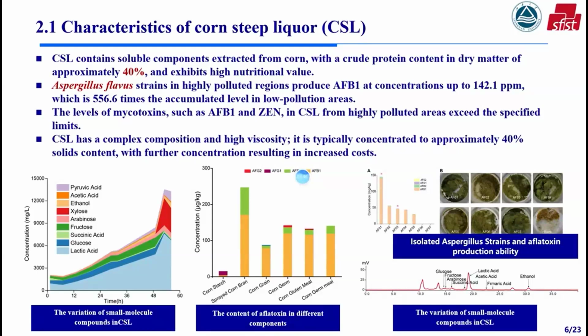susceptible to aflatoxin contamination. Strains isolated from different regions have different toxin-producing capabilities, and those from high contamination areas have significantly higher aflatoxin-producing ability than those from low contamination areas. Strains from high contamination areas can accumulate up to 142.1 ppm of toxins, which is more than 500 times that of low contamination areas. Besides aflatoxins, ZEN is also frequently detected in CSL. CSL is usually concentrated to 40% for storage and transportation. This concentration not only increases viscosity, but also further raises mycotoxin levels, making it difficult to use in feed.